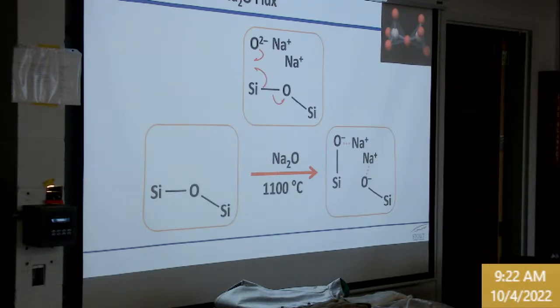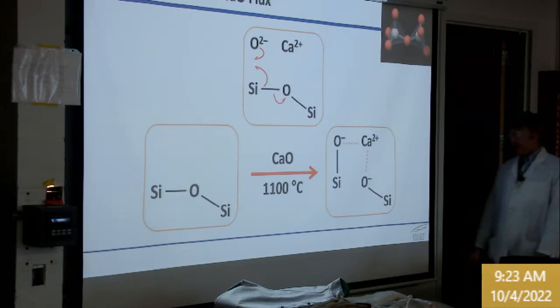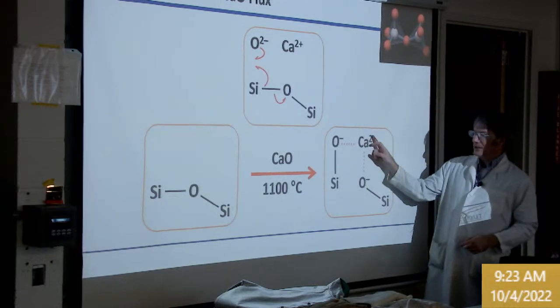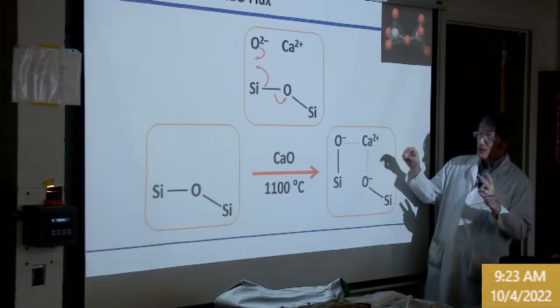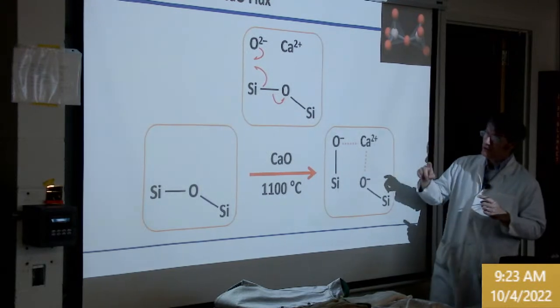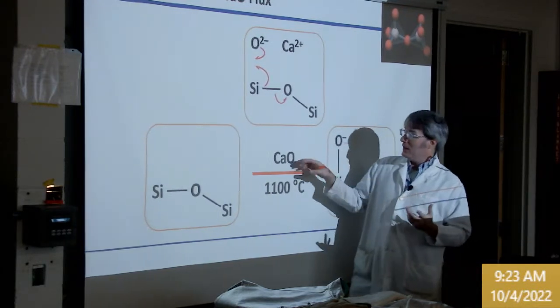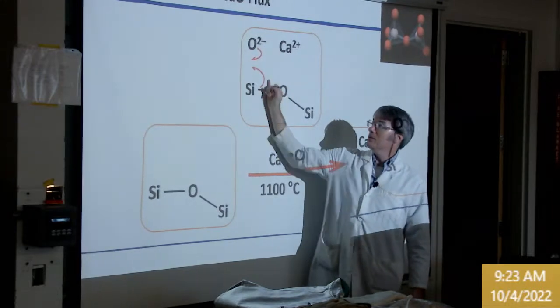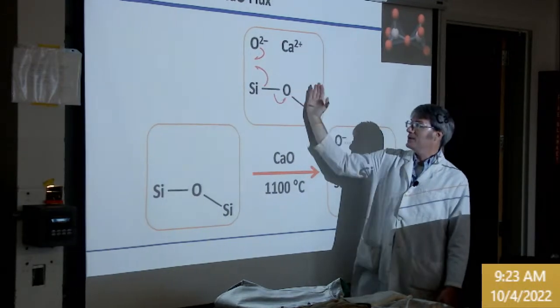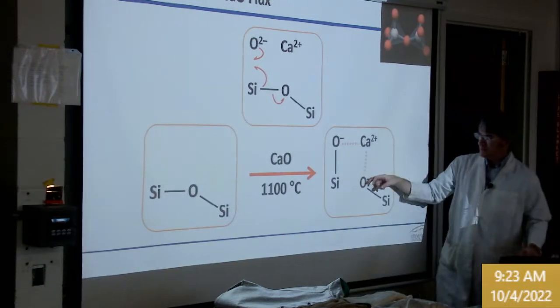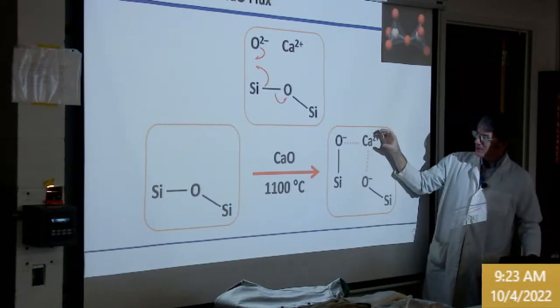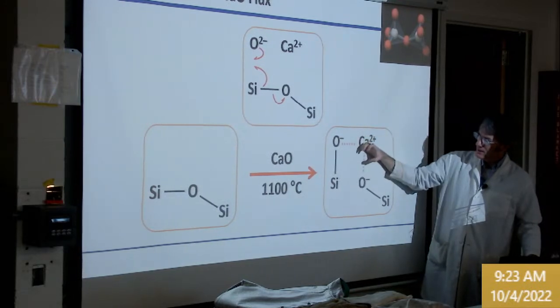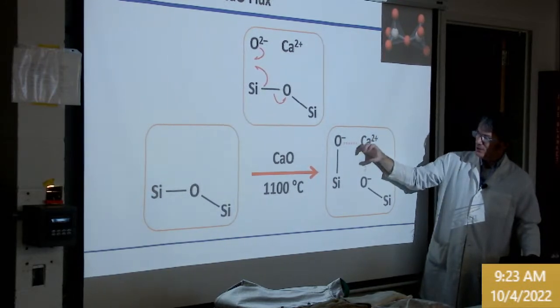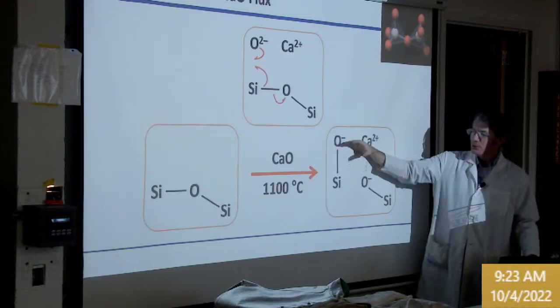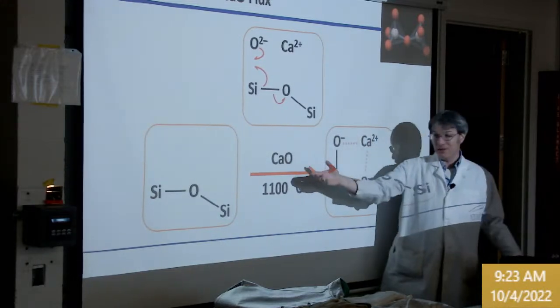Well, the sodium is just a flux, where calcium is a flux stabilizer because calcium is a 2+ ion. So instead of having two sodiums and an oxygen, we have one calcium and an oxygen. The story looks a lot alike. The oxide attacks this bond, forms a new bond, breaks this bond. We end up with two pendant oxides. But now the calcium, because it has a 2+, can sit in between those and still form an association where the previous bond was. Now that's going to migrate.